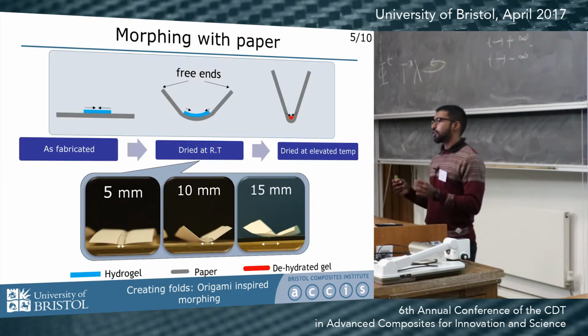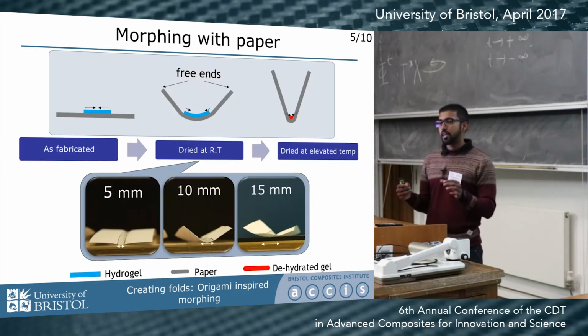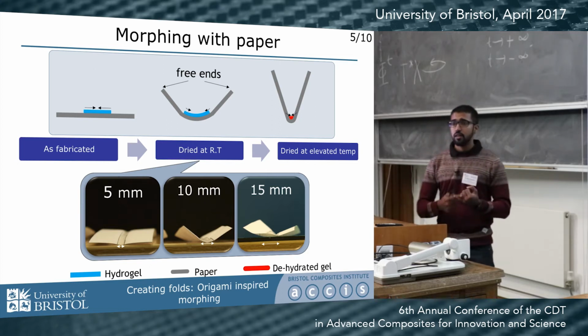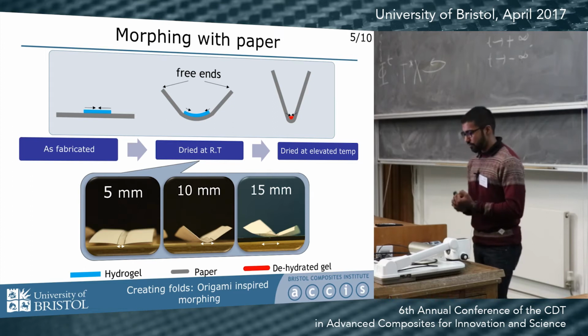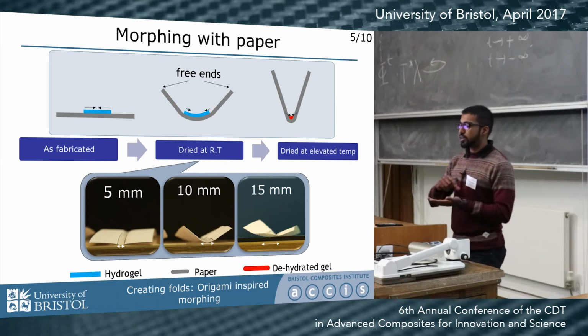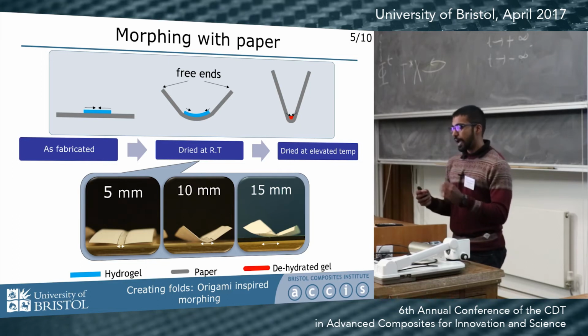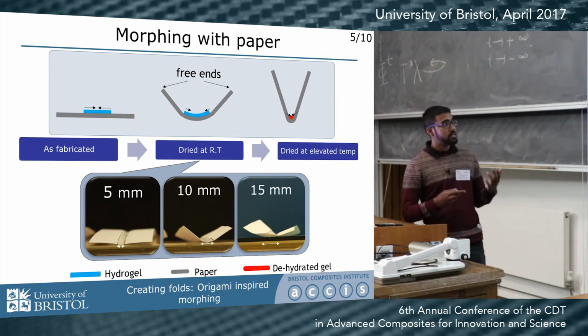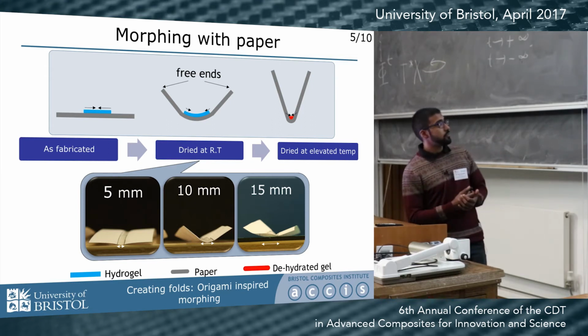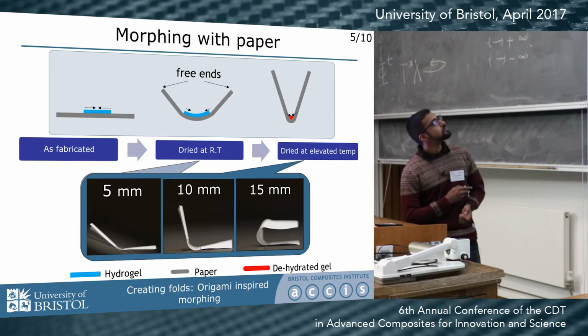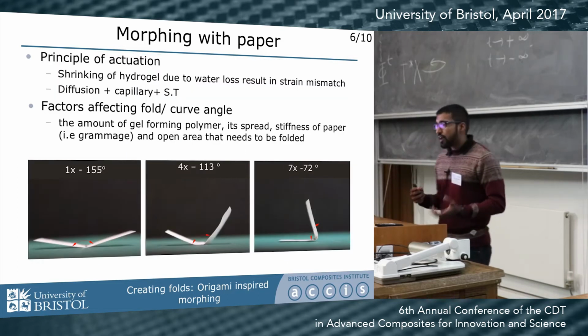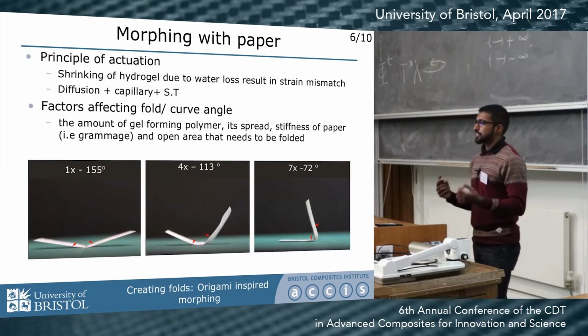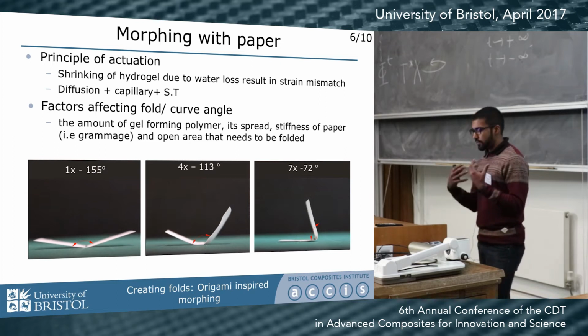Here, we present a methodology to realize folds and curves in fibrous substrates such as paper without the complexity in terms of material, fabrication, and chemistry involved. We pattern fold lines on paper with a specific formulation of hydrogel, and the drying results in morphing, which can be maximized by drying at an elevated temperature. Shrinking of hydrogel due to water loss results in strain mismatch, which drives these forms.